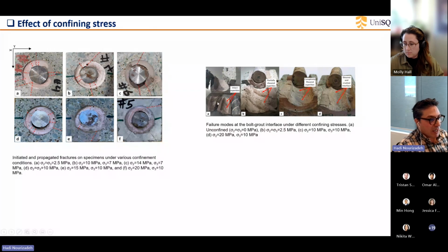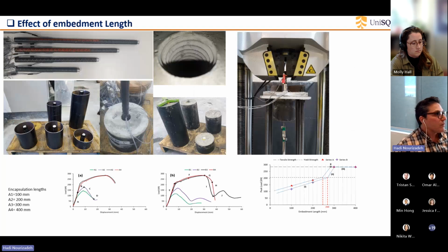Also, we sliced the sample and we realize that when we don't have any stresses, the failure is due to dilation or splitting of the sample, which is obvious. But when we increase the load, in addition to the shear failure, which occurred at the bolt-grout interface, we also have some damage as well. This is why, when damage reaches a specific amount, we don't have an increase in the bonding strength of the bolt.